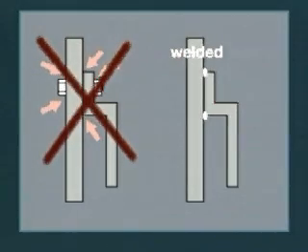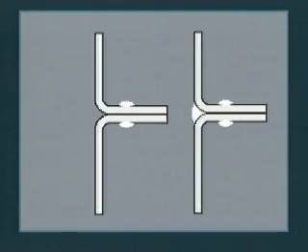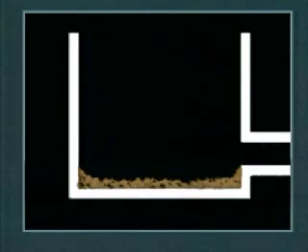For many architectural applications, a suitable mastic is often used to eliminate the crevice in mechanically fastened joints. Similarly, a sealing weld run may be used to eliminate the crevice in this type of welded joint. The local environment can also become more aggressive if sludge buildup occurs. So, good designers always eliminate sludge traps and ensure free-flowing drainage.